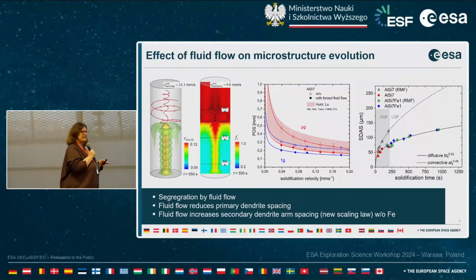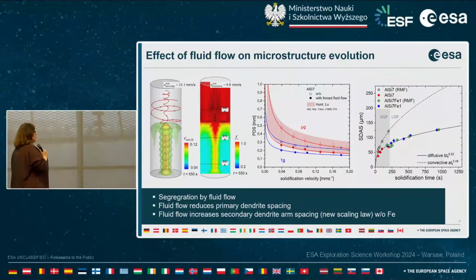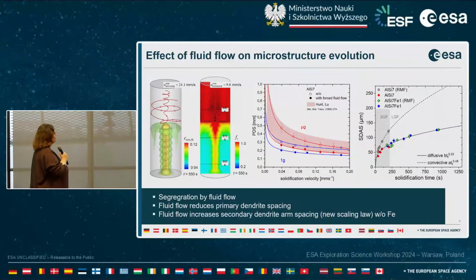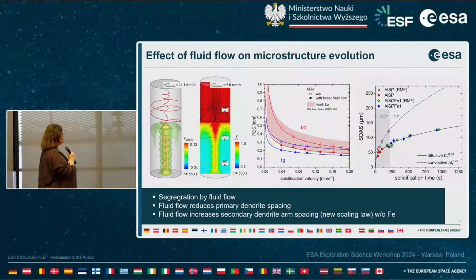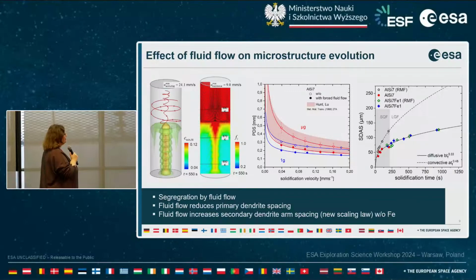You change the kinetics in principle, and this has also been implemented in the models. So now we are coming to the results of the iron-containing alloys, independently of whether the samples were solidified with or without rotating magnetic field. The green and the blue squares here are all lying on the 1/3 curve.